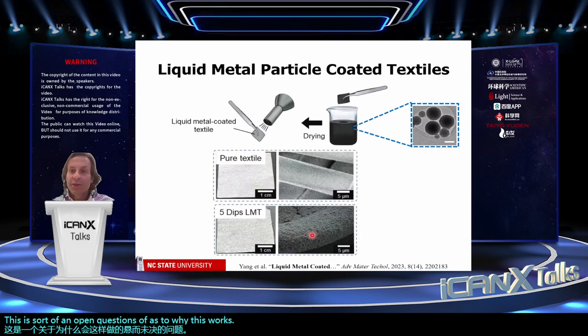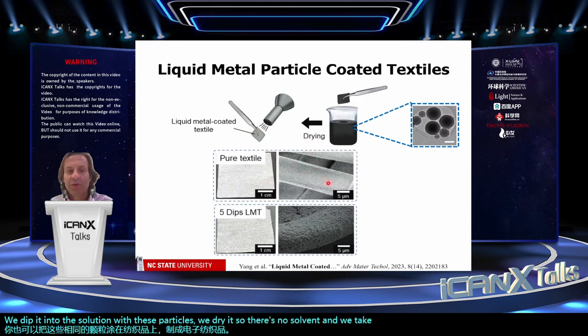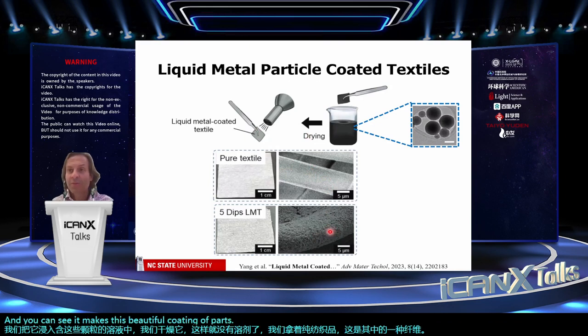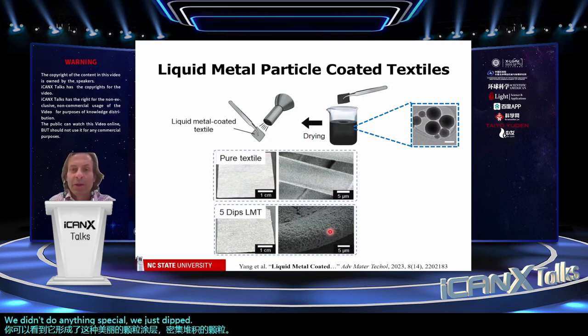You can also take these same particles and coat them onto textiles to make electronic textiles. Here we take a fabric, dip it into the solution with these particles, and dry it so there's no solvent. We take the pure textile, and here's one of those fibers, and you can see it makes this beautiful coating of densely packed particles. We didn't do anything special, we just dipped it in there. And these, again, are not conductive.